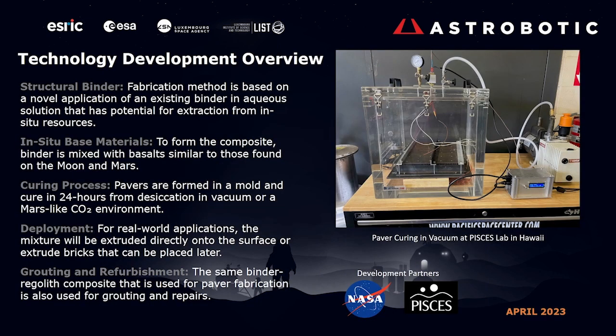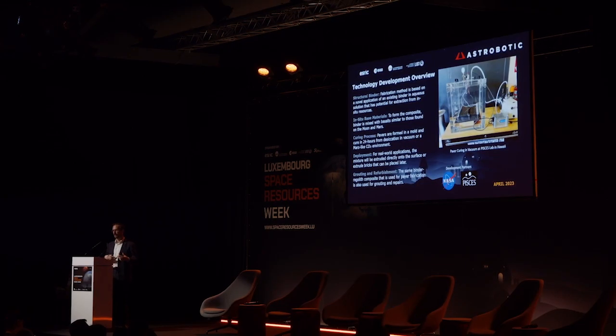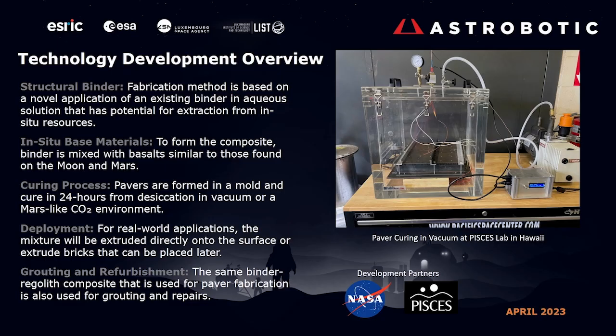There we go. This is an image of a vacuum chamber that we were using to cure these materials. We made a number of samples of these pavers because we want to try this material out as a prospective landing pad material. We cured some of them in full vacuum, or as close to vacuum as you get, 10^-4, 10^-5 torr, something like that, and some of them in a simulated Martian environment where we had 1 kPa of carbon dioxide, to see how the different environments affect the formation of the landing pads. As I noted previously, we cut some of them in half and grouted them back together. So that left us with a number of these samples.